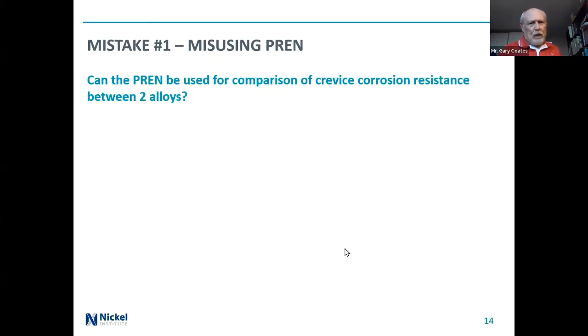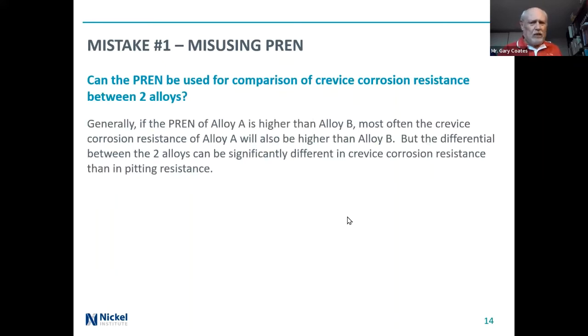Can PREN be used for comparison of crevice corrosion resistance between two alloys? And the answer is there is a general correlation. So if the PREN of one alloy, alloy A, is higher than alloy B, most often the crevice corrosion resistance of alloy A will be higher than alloy B. But the difference between the two alloys can be significantly different. And so we've seen it where, for example, the pitting resistance of alloy A is much higher than alloy B, but the crevice corrosion resistance of alloy A is only slightly higher than alloy B. And so you have to be careful when using it in terms of pitting and crevice corrosion resistance, but it's somewhat close.